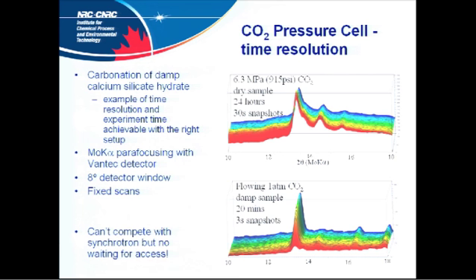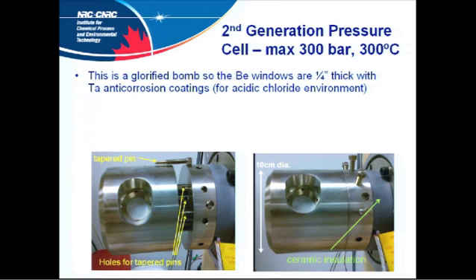And this reaction is so fast under pressure that you just have no chance of seeing it on a lab instrument. At atmospheric pressure, you do actually have a chance. You can actually see some of the reaction going on. That's basically 3-second snapshots. As I say, you're never going to compete with a synchrotron as far as time resolution is concerned, but the right experiment can be done, as long as your time scale is okay.